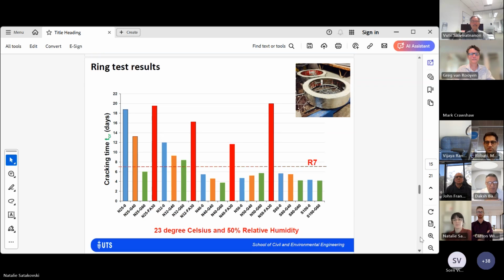That's important. We have been testing a lot of different concrete with different strength and different binder composition. The criterion is no cracking before 7 days, so R7. And as you can see, there's a lot of concrete that actually are cracking before 7 days. Only few of them are not cracking.